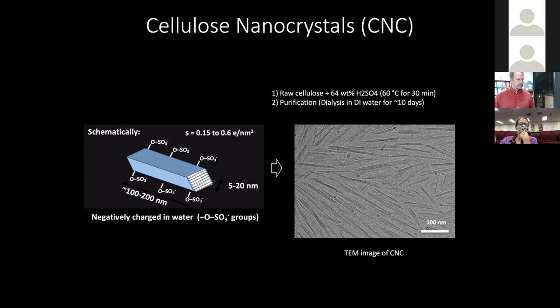As pigments themselves, they are pretty good because they are highly thermally stable. Being only the crystalline part of the cellulose, the thermal degradation is around 250 degrees. We have used them with some collaborators for hot embossing, heating them up to 100 degrees to embed them in polyurethane films, and the color was maintained. They become a bit brownish above 100 degrees if you keep them for long, because of a little bit of caramelization, since it's essentially sugar. But the other characteristics are pretty good. I wouldn't see any problem if you put them in a normal binder; they would last as long as the titanium dioxide pigment in terms of outside durability.